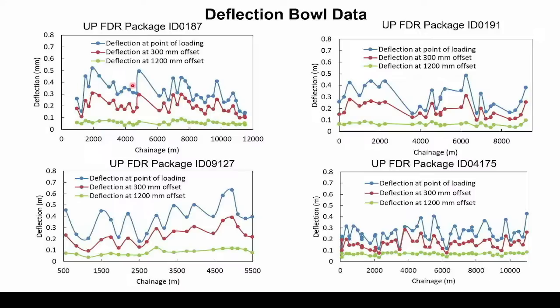And therefore, it is very imperative to consider innovative technologies so that we can reduce such variations that come into the picture. But overall, what you can see is the D naught deflection, that is the maximum deflection under load, varies from 0.1 to 0.5 mm. In extreme cases where there is a localized failure, it even goes to 1 mm.